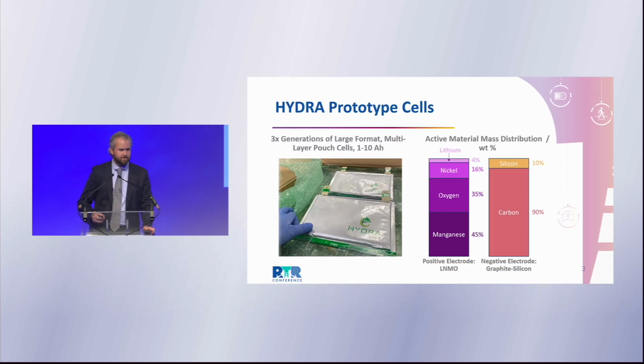So what did we do? Well, we created 3 generations of large format multi-layer pouch cells that range in capacity between 1 and 10 ampere hours. And this is important because when we're doing materials development, often things work very well on small scale, very well on coin cells, but don't necessarily scale up to industrially relevant pouch cells. So by doing that from the beginning, we tried to make sure that the developments and the materials that we create in Hydra are relevant for the industry.